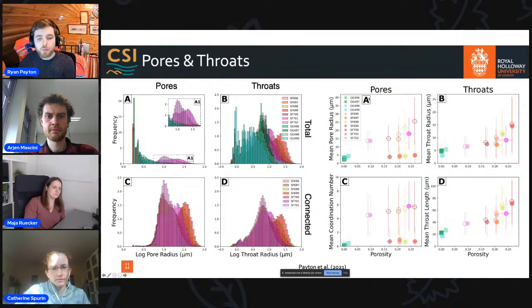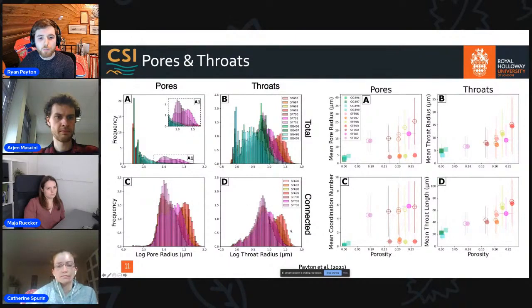Over on this side, we measure a few different characteristics such as pore radius, throat length, and coordination number. And the hollow circles are for the connected porosity, and the filled circles are for the total porosity. Now we have a discrimination between the two here because of those many small pores which are incorporated into the total porosity, but the hollow circles aren't showing that, because as we see over here, the small pores and throats aren't contributing. So as expected, the porosity is increasing as the pore radius and throat radius and coordination number are increasing as well. So we've been able to provide a good detailed characterization of these samples.